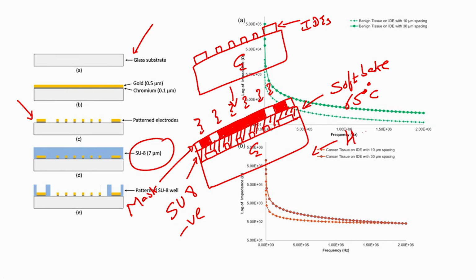followed by hard bake. In this case, after exposing, you have to go for hard bake, not like other kinds of photoresist, and hard bake is done at 95 degree centigrade. Again, the time depends on the thickness of the photoresist, followed by photoresist developer. That is the difference between SU8 photoresist and other photoresist. In other photoresist, we go for soft bake at 90 degree, followed by loading the mask, exposure, developer, hard bake. But in this case, we go for soft bake, then exposure, then hard bake, then photoresist developer. And when you develop the photoresist, SU8 being a negative photoresist, the area which is not exposed to UV light will get weaker, and that is why after developing with photoresist developer, the pattern will look like schematic